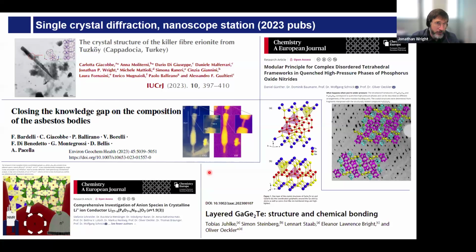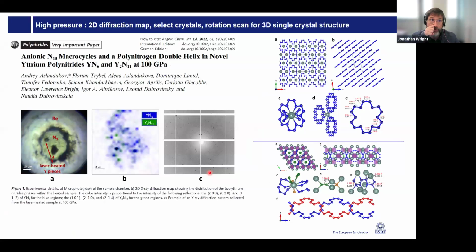And the small crystals is an important part of what we do, that you can measure very small crystals. And I think electron diffraction or electron microscopy has been key to getting those crystals onto the beamline and selecting the samples. So a method that's been developed and is a very exciting development for us at ID11 is measuring samples inside of diamond anvil cells. So this is an approach that was developed by Leonid Dubrovinsky and Natalia Dubrovinskaia.